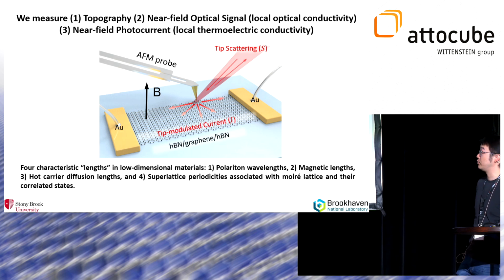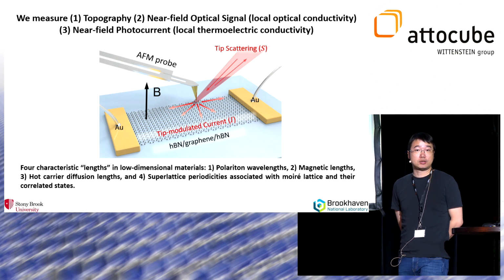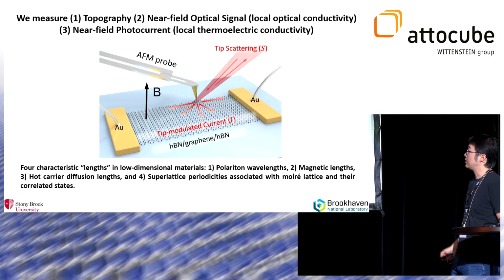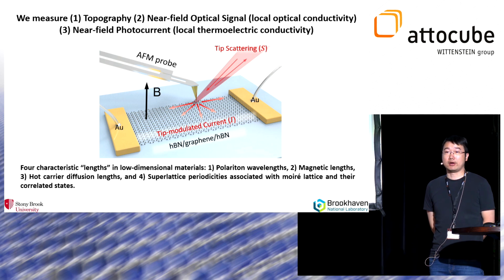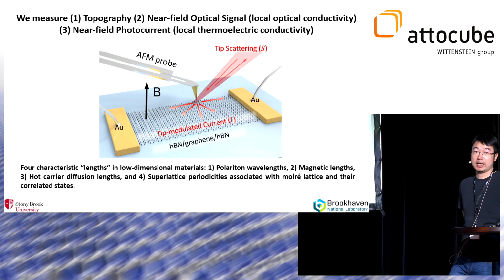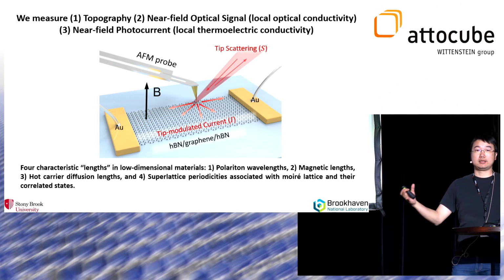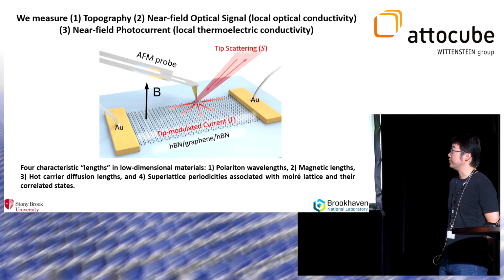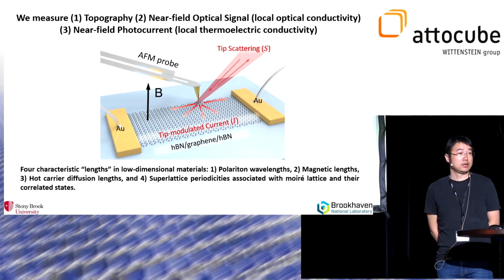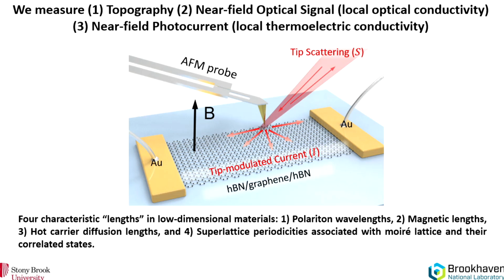So with magnetic field, we can basically characterize 4 length scales simultaneously, right? One is the polariton wavelength. The second one is the magnetic length, which in graphene is 10 nanometers at 7 Tesla magnetic field. Of course, this magnetic length is smaller when you have higher magnetic field. You can also detect hot carrier diffusion lengths through these photocurrent measurements, and superlattice periodicities if you have moiré arrays. And you can imagine that if all these 4 length scales intervene with each other, you can have many interesting many-body physics, especially for charge-neutral systems.